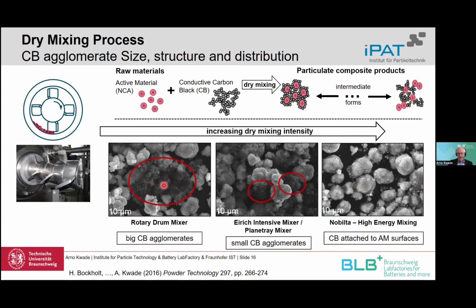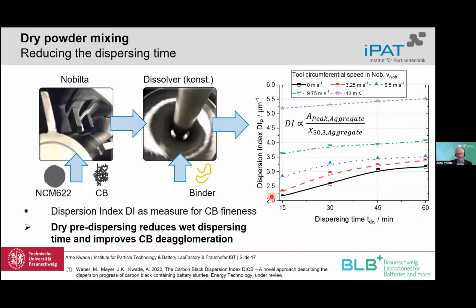If we have, let's say, a high intensity mixer, then the agglomerates are much smaller. Already the first aggregates are sitting on the surface of the active material particles, and we do it in an extreme case. Then we really coat the active material particles with the carbon black, which is maybe too extreme, but you can see that also later. So something in between is what we need at the end.